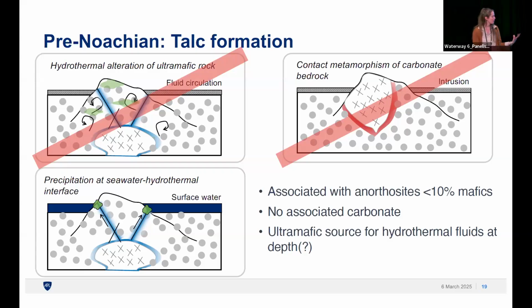And because we see basically that talc is pretty spatially associated with the anorthosite, which does not provide a mafic component or the Mg that you need to make the talc, we don't think it's the first one on the upper left.